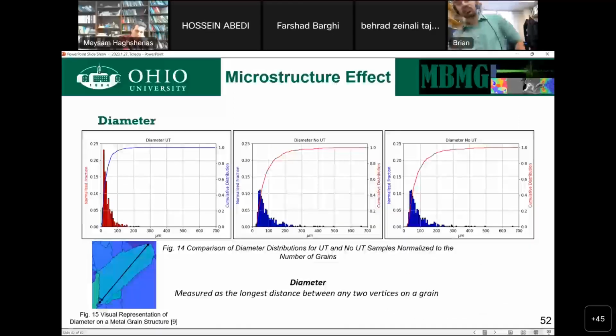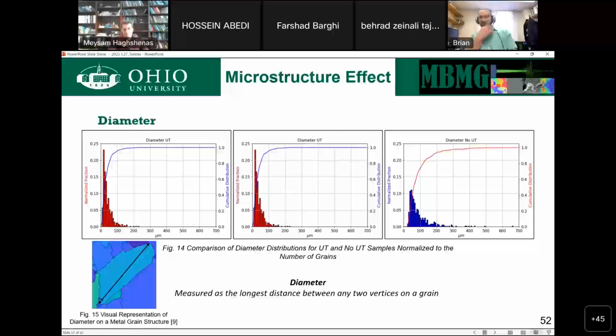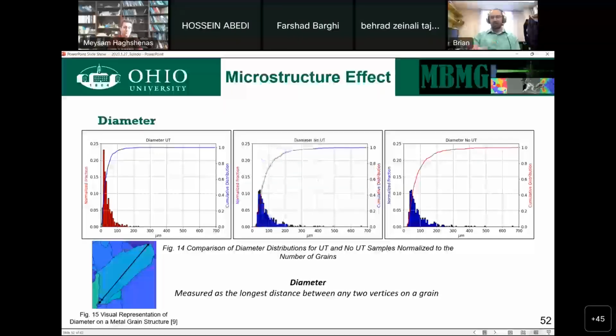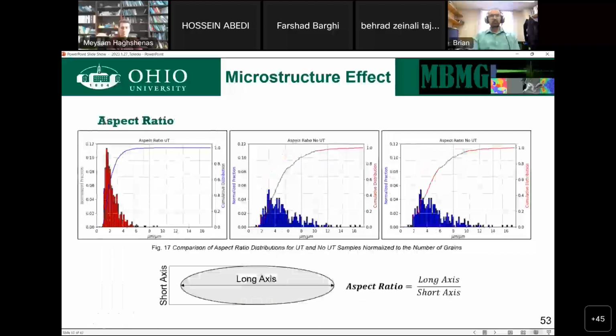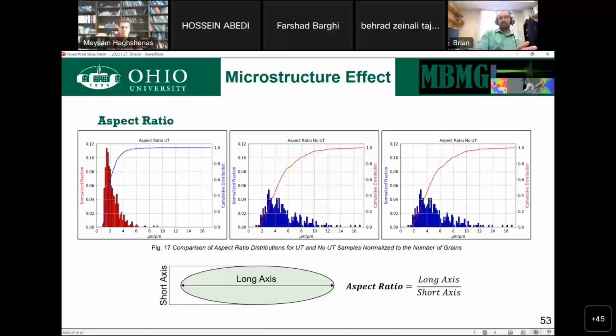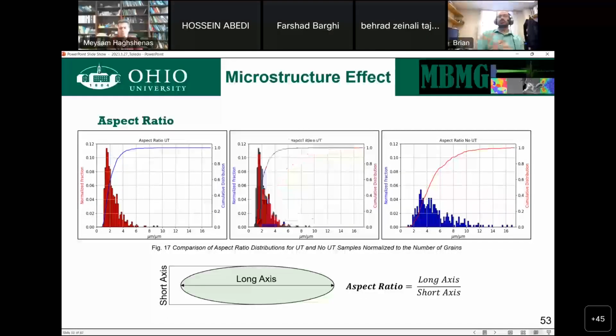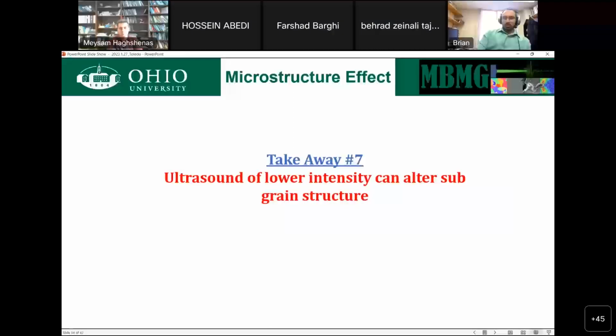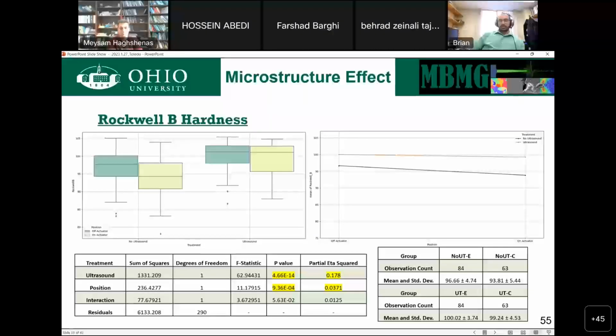And if we quantify some of the properties in the grain structure for high enough intensity, you can very easily see that the ultrasound ones, which are represented by the red, and the non-ultrasound represented by the blue, there's a shift towards the smaller diameter grain if we take that area and assume that's the grain. Same thing on aspect ratio. There's a shift down towards 1 aspect ratio, getting closer to equiaxed grains, not exclusively, but more consistently. So that leads to the lower intensity, ultra subgrain structure.